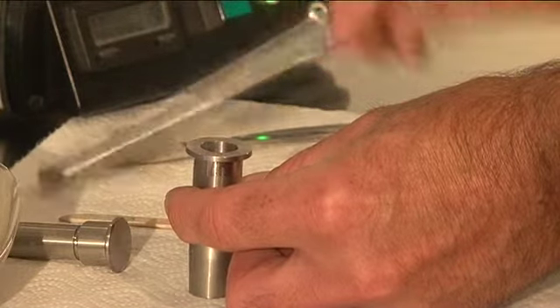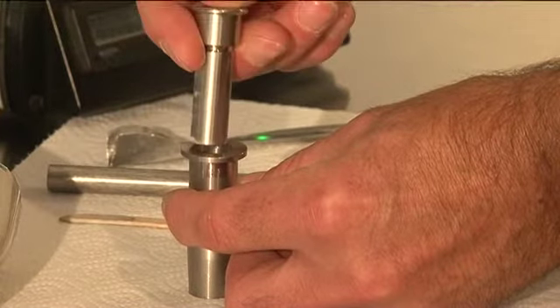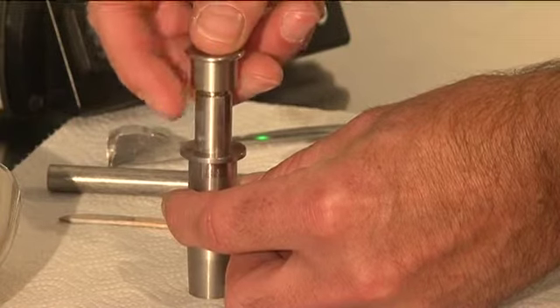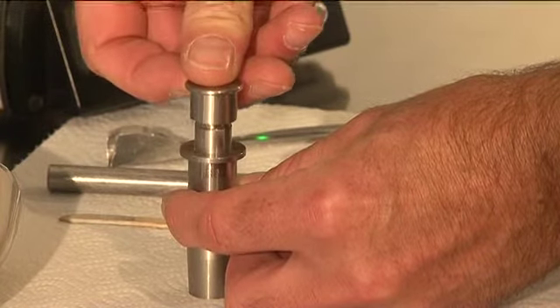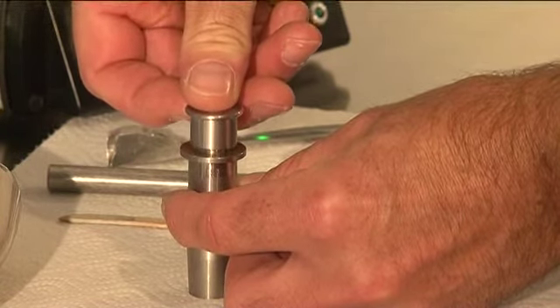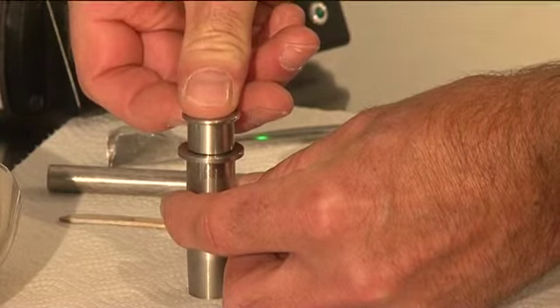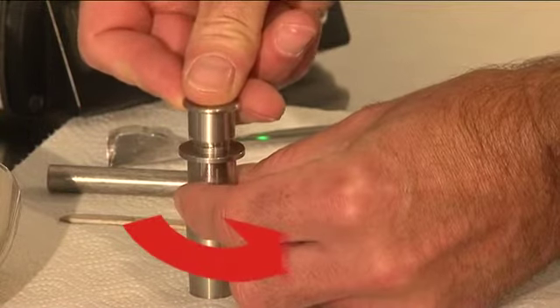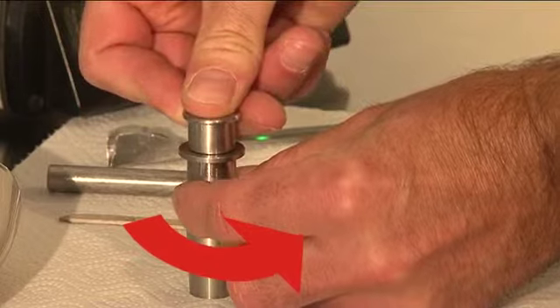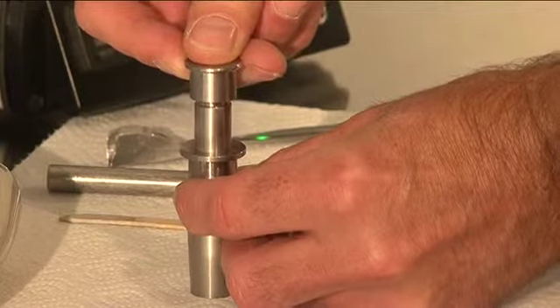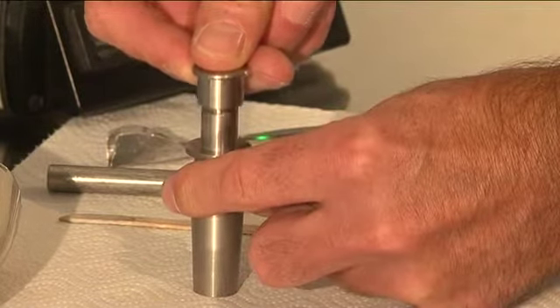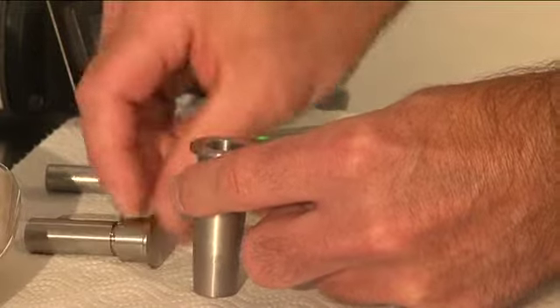Guide the plunger into the measuring cell and carefully press it onto the powder bed to compact it. Press it so that the lower face is in contact with the upper edge of the cell. Now raise the plunger approximately 5 mm, rotate it through 90 degrees and press it once more onto the powder bed. Carefully withdraw the plunger from the cell.